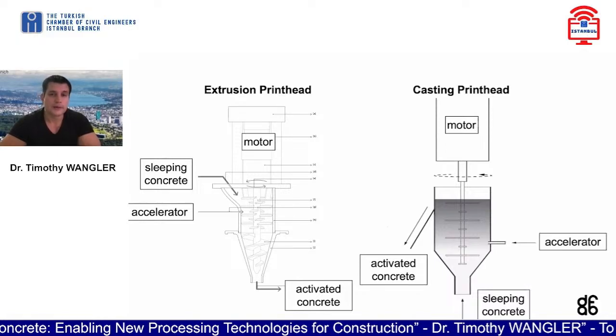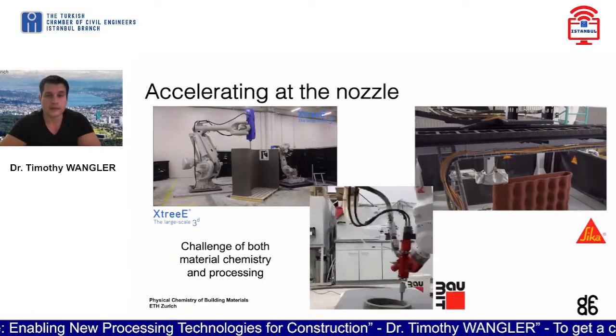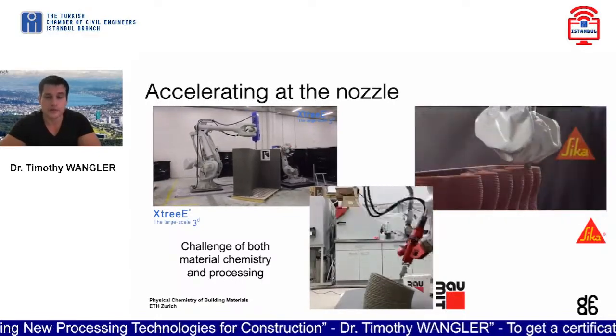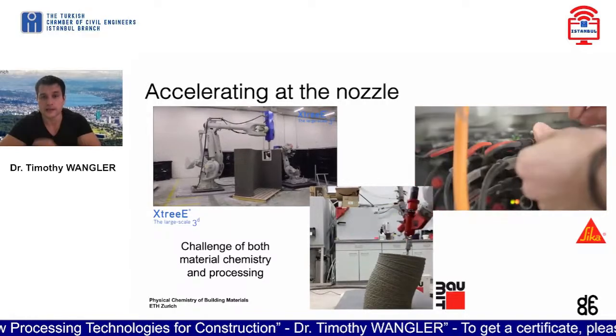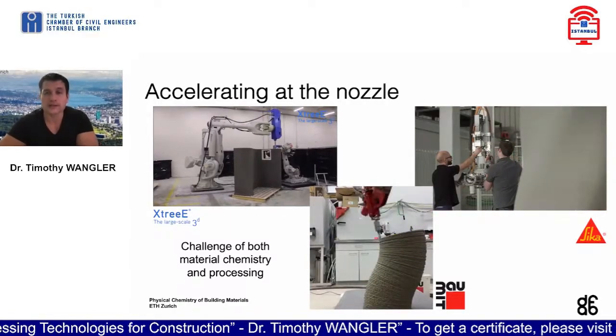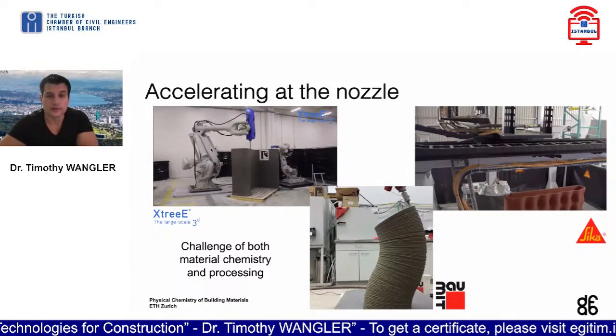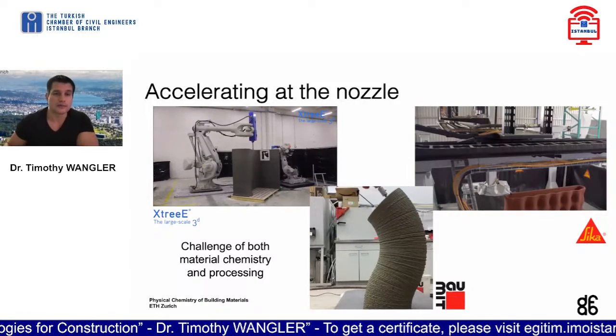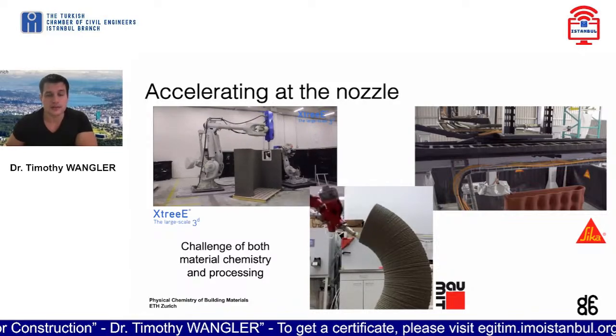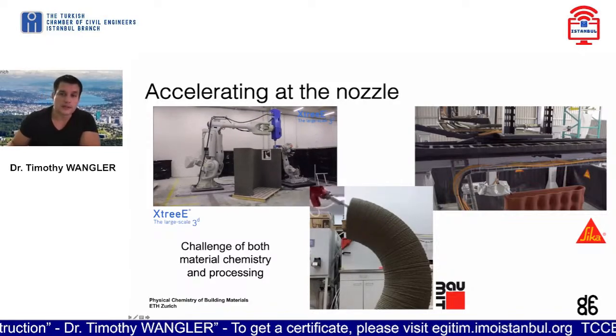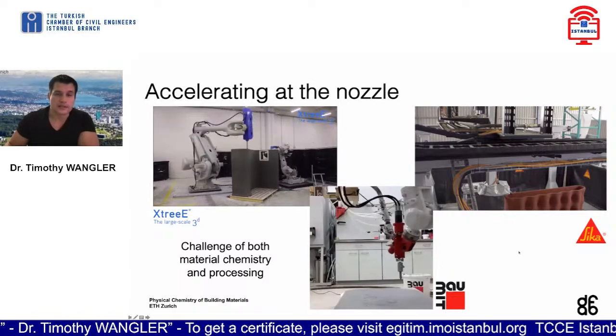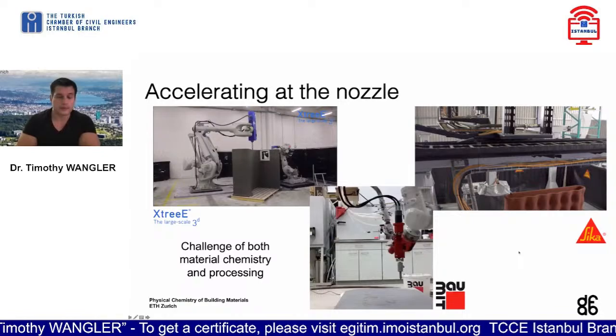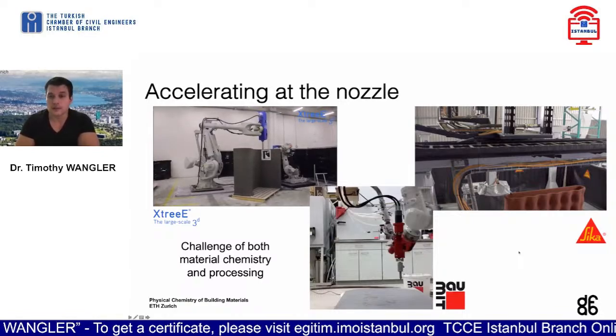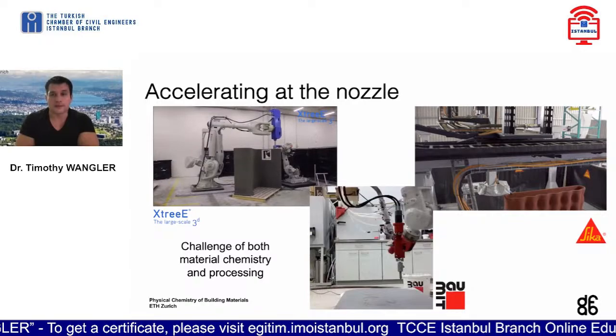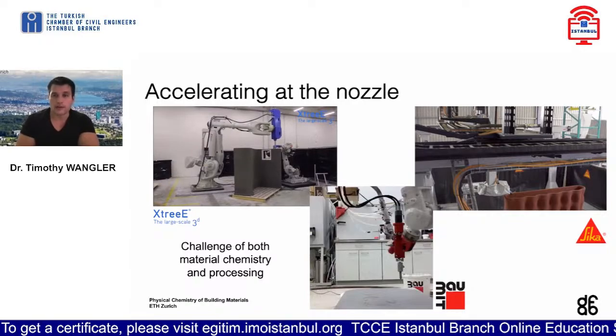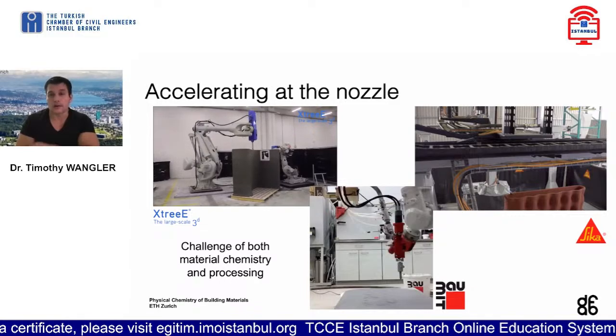And this is really the state of the art from industry as well. There's really only 3 industrial players when it comes to very fast vertical build rates with the addition of accelerator close to the point of placement. Of course, the system from the startup in France, Extree, the Baumit system developed in Austria, and Sika, of course, has made a lot of headlines with their really great 3D printing system. But this is really what allows you to build at rates of anywhere from 1 to 5 to even 8 meters per hour vertically.